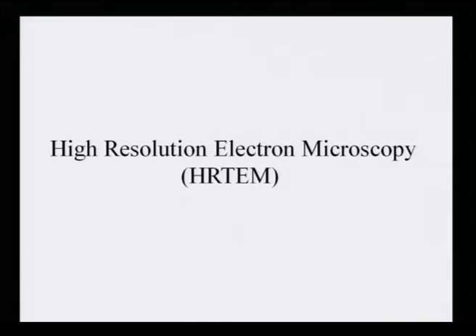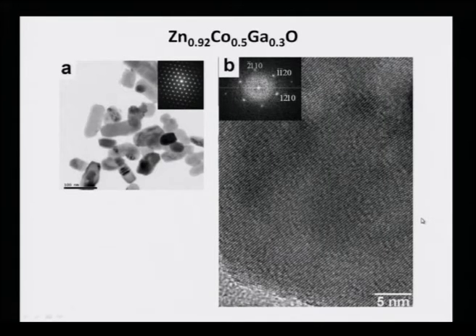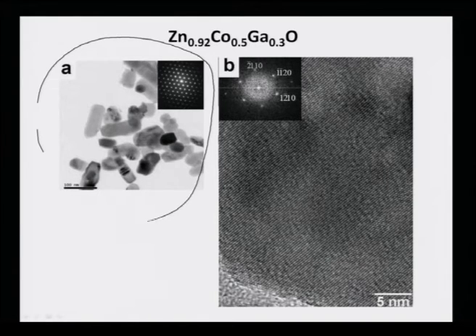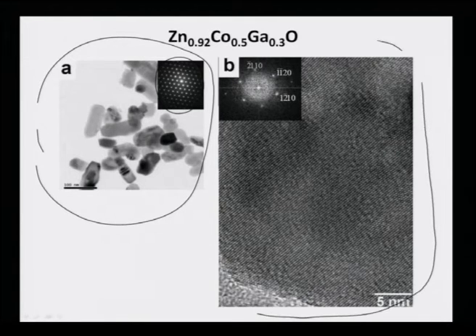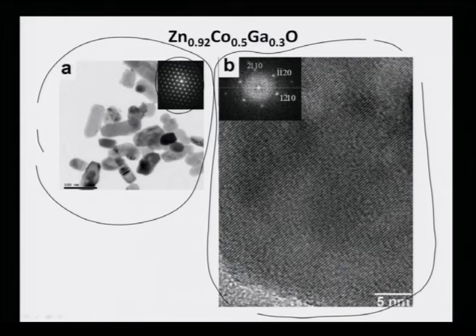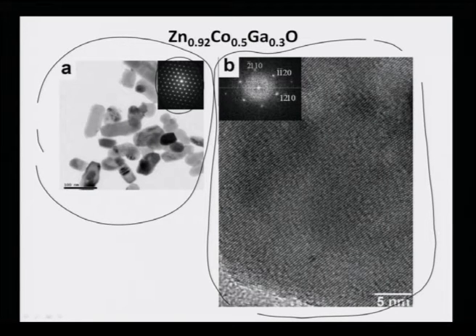First I will show some examples. The left-hand side image shows the normal bright field image of zinc oxide doped with cobalt and gallium, with an electron diffraction pattern taken along the [0001] zone axis. The right-hand side image is taken from one such crystal showing the lattice fringes — the columns of atoms are clearly shown. If we measure the distance between two atomic layers it should correspond to the d-spacing of the (0001) plane of zinc cobalt gallium oxide.